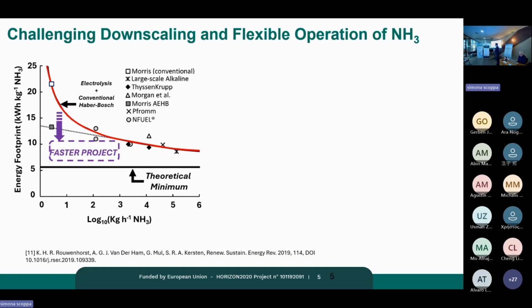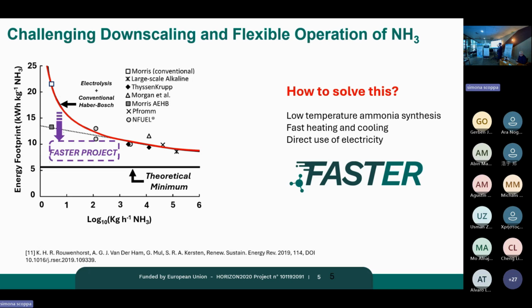And so that's where the FASTER project comes along. And the idea there is that we use absorption enhanced Haber-Bosch coupled to a low temperature ammonia synthesis catalyst. So these two options essentially lower your capex, lower your opex, because you don't need to go to very high pressures, and therefore you don't have such a large energy loss.